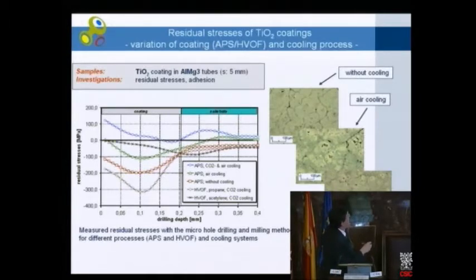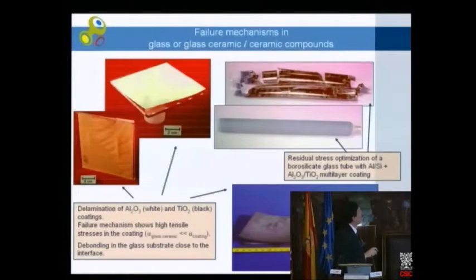The last example to show the importance is the variation of the cooling. 3 times the same material, the same substrate, the same geometry, the same design, just varying: without any cooling, the red line, with a traditional compressed air cooling, and quite intensive cooling with liquid carbon dioxide plus compressed air cooling. And you see again, we can vary the stress distribution by more than an order of magnitude. So, we can summarize. The substrate plays an important role, the heat transfer plays an important role, the mismatch in thermophysical properties plays an important role, and there will be further important factors that will influence these stress distributions, and they are essential for the reliability and for the functionality of our final product.